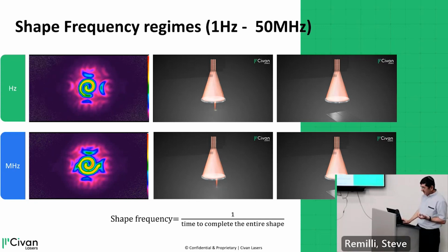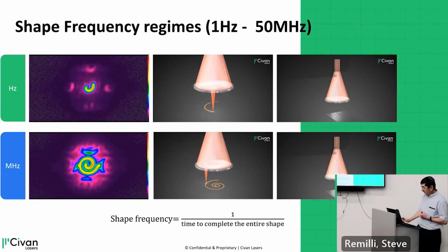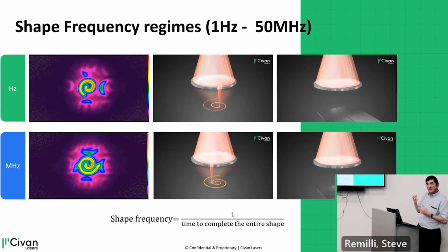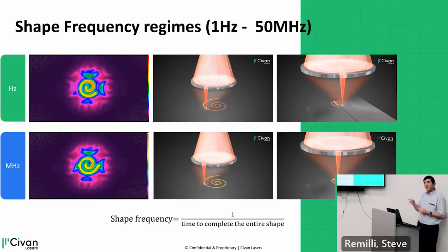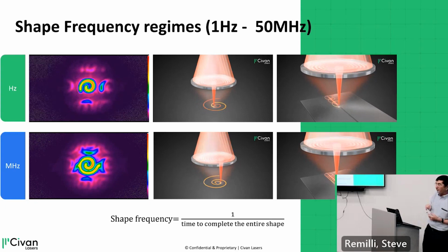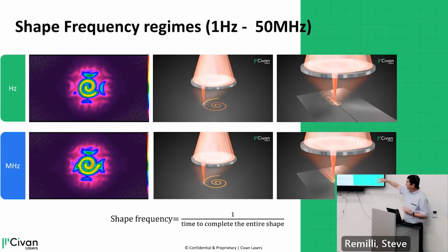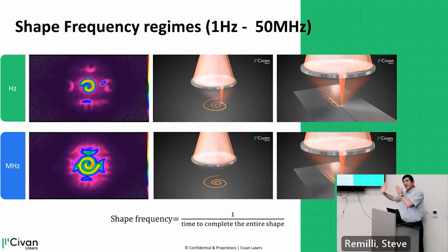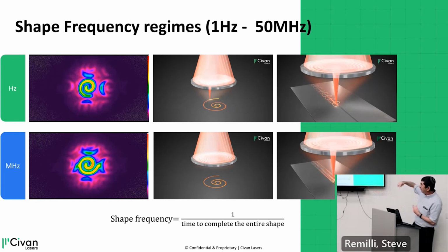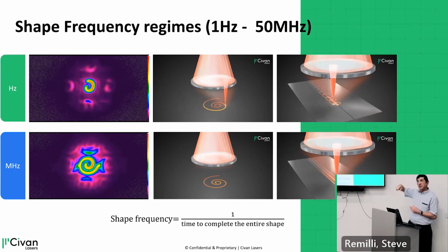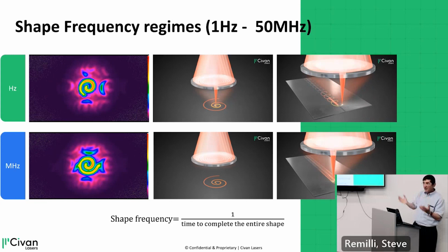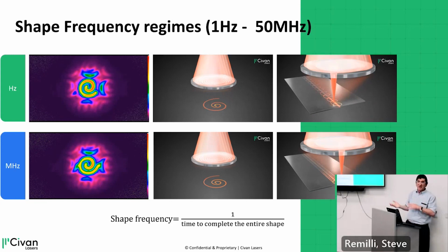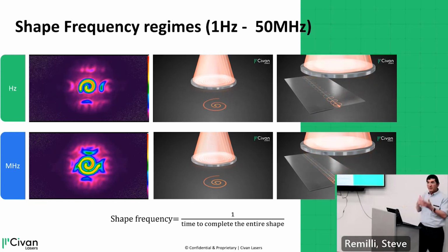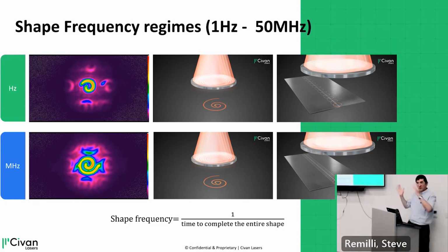And of course, it's important, firstly, because of the dynamics inside the melt pool that are completely different if you move the keyhole slowly or fast. But also, when you correlate it with the feed rate, it means, are you going to repeat your motion inside the melt pool a few times or a few thousand times, right? So it's completely controllable. And again, just by the click of the button, you can do whatever you want.